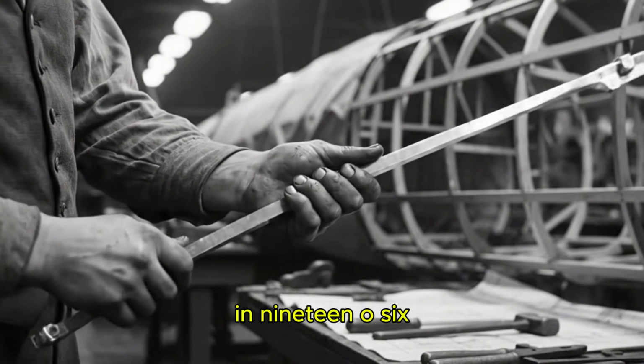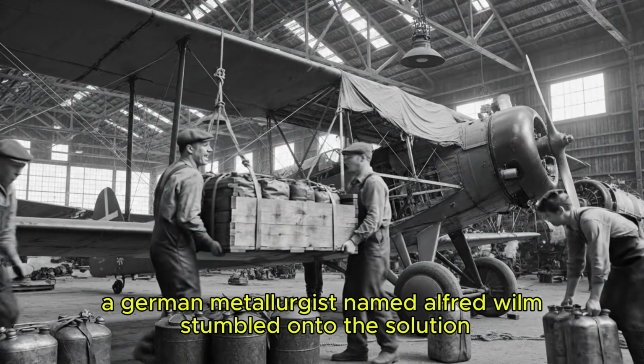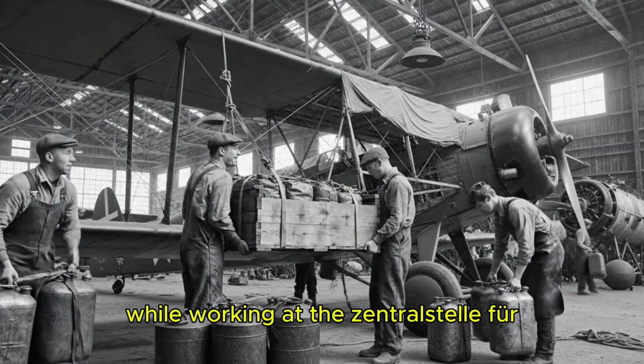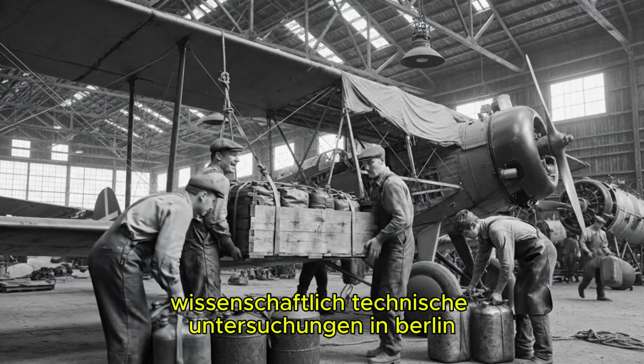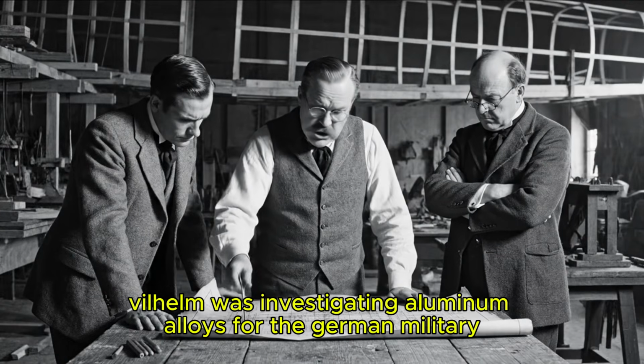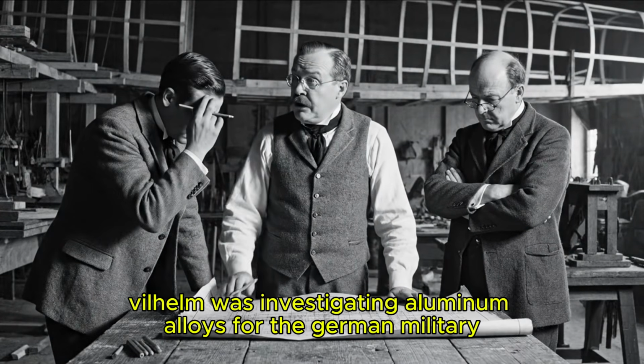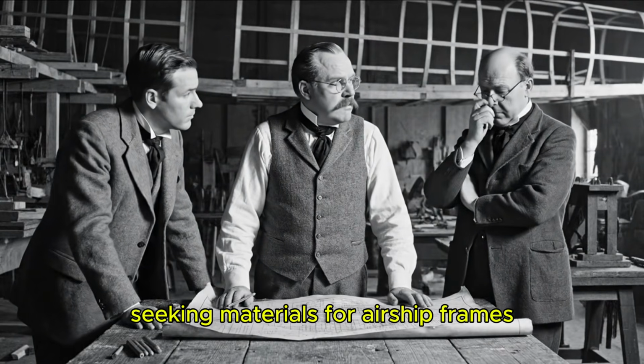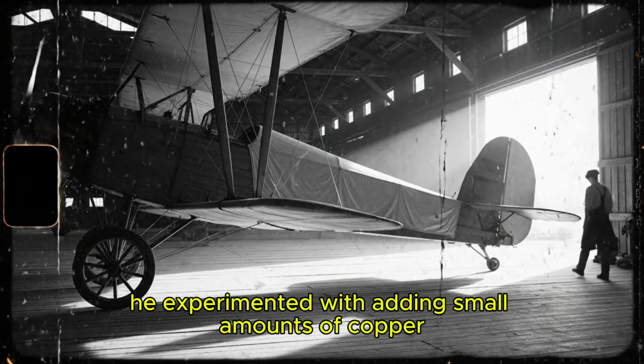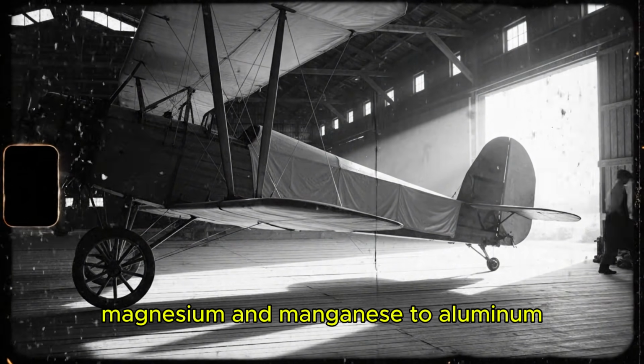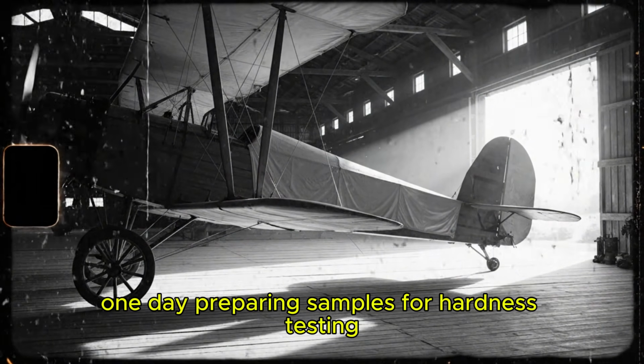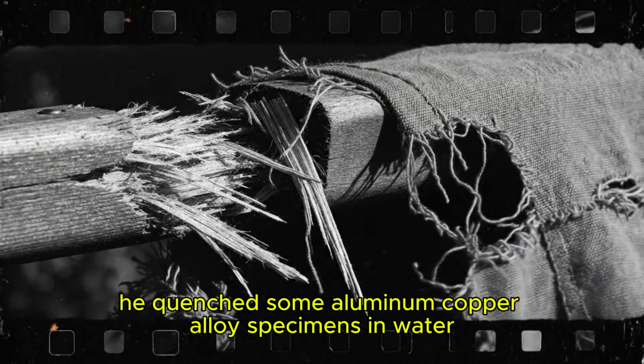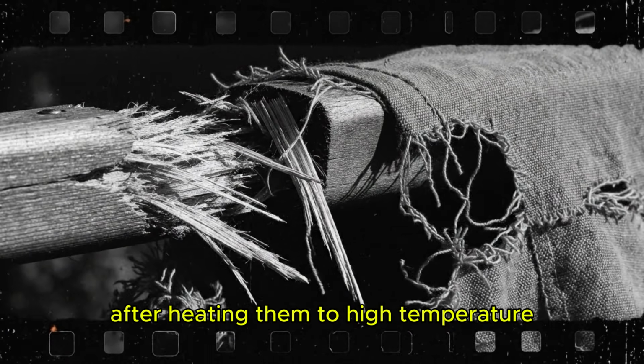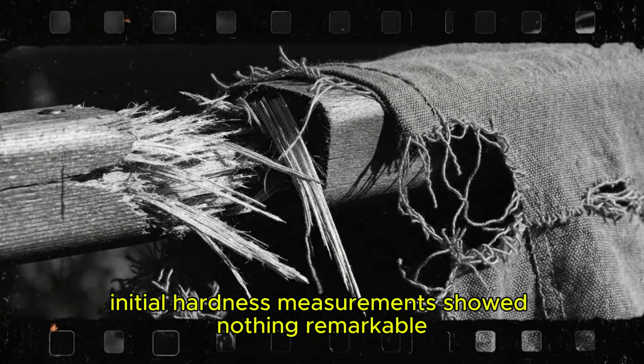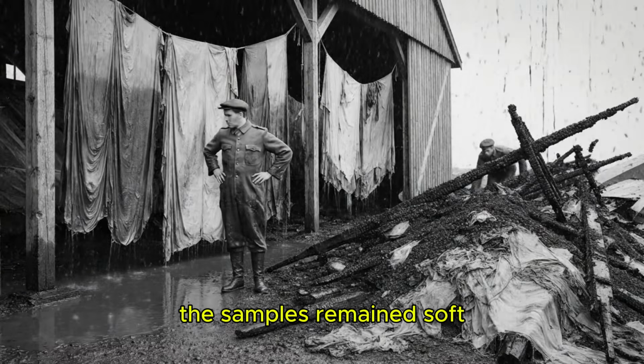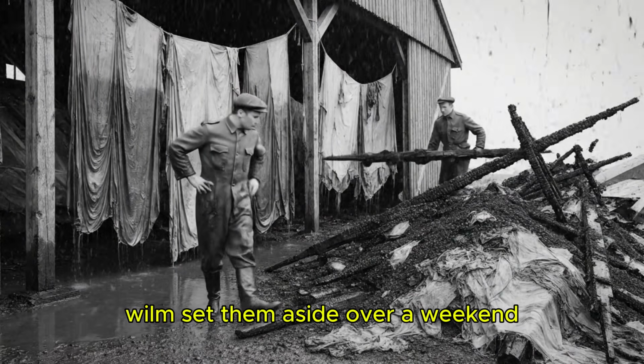In 1906, a German metallurgist named Alfred Wilm stumbled onto the solution while working at the Zentralstelle für wissenschaftlich-technische Untersuchungen in Berlin. Wilm was investigating aluminum alloys for the German military, seeking materials for airship frames. He experimented with adding small amounts of copper, magnesium, and manganese to aluminum. One day, preparing samples for hardness testing, he quenched some aluminum-copper alloy specimens in water after heating them to high temperature. Initial hardness measurements showed nothing remarkable. The samples remained soft. Wilm set them aside.